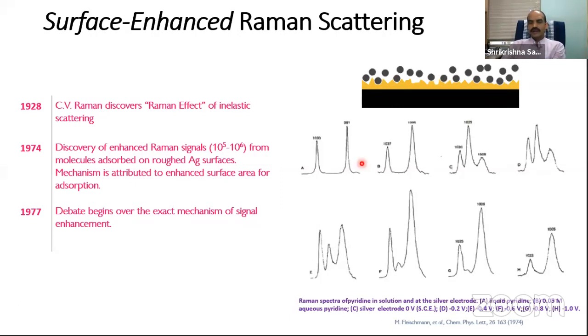surface, and because of the electrochemical treatment, there was some electrochemical etching. That etching actually caused a rough silver surface. When he optimized this treatment at different voltages, he observed that when he gave a 1 volt treatment, the silver oxide peak, which was at the center, decreased. The negative 1 volt treatment I'm not interested in. What we are interested in is that if you make the surface properly rough, you just see the pyridine molecule Raman spectrum, but not the silver oxide. So this intensity is much higher compared to the silver oxide peak, and therefore I am able to detect a very small amount of this.